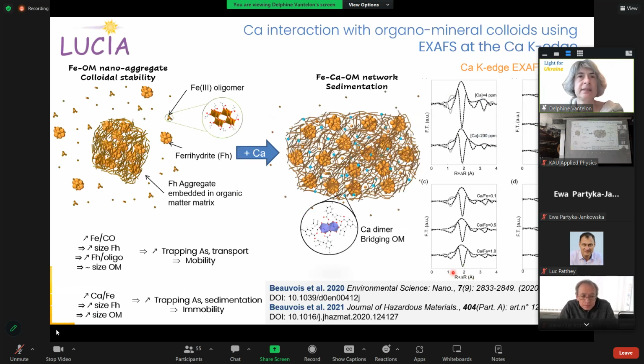And then when it is released, it is transferred in the hydrosphere and can be trapped by colloids. And here is a study of the structure of colloids and how it evolves with the variable physicochemical parameters where it is sitting. Here the study is the evolution of calcium concentration. So when there is calcium, it interacts with the organic matter, forming dimers, bridging the organic matter. And this was demonstrated by the EXAFS at the calcium K edge performed on the different colloids.